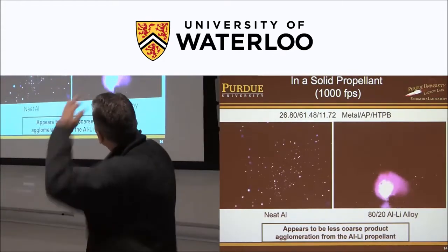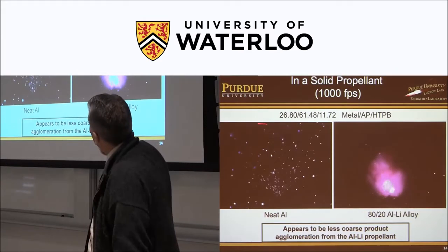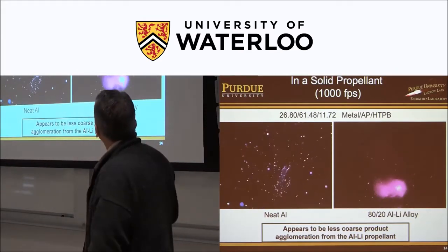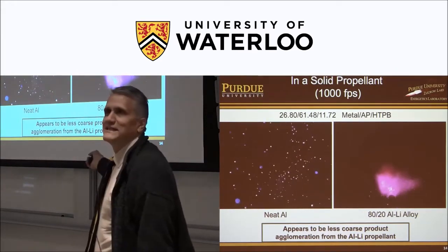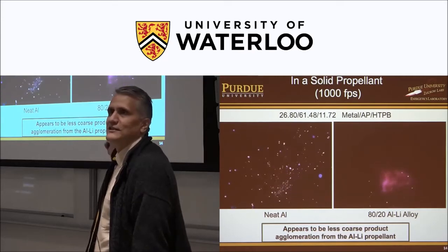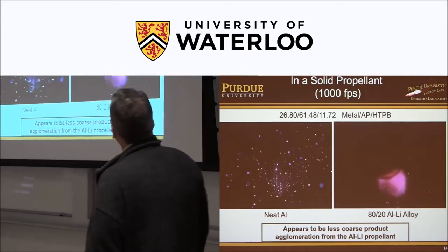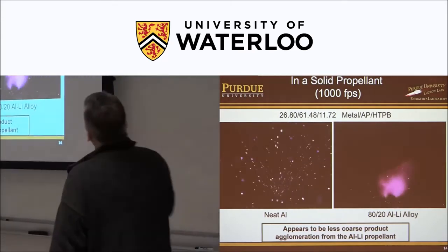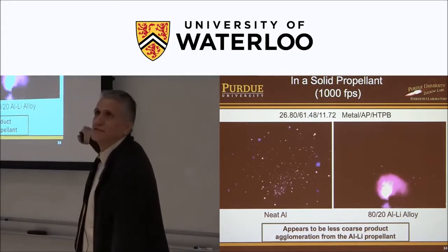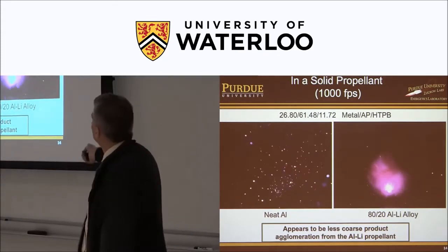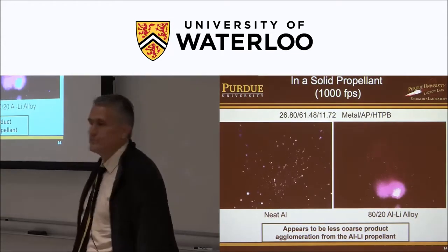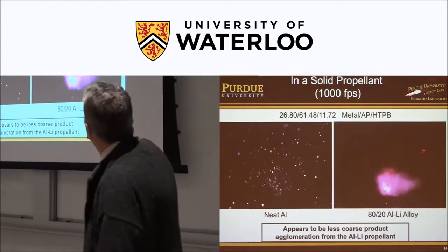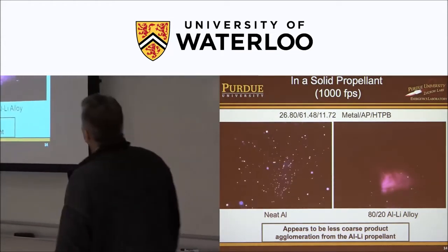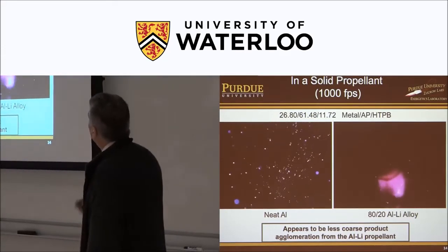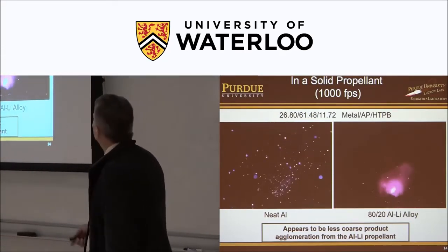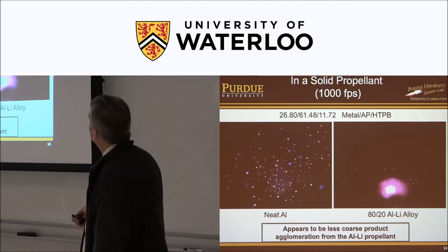A couple things I notice on this is you see particles burning far away from the strand. Here, the biggest thing that stands out is the color. And that's lithium will burn kind of a magenta. To me, it looks pink. And then look at all the dark space. What does that mean? Those particles are pretty much consumed and done before they move very far downstream. And also kind of seems to be kind of exploding in an interesting way.